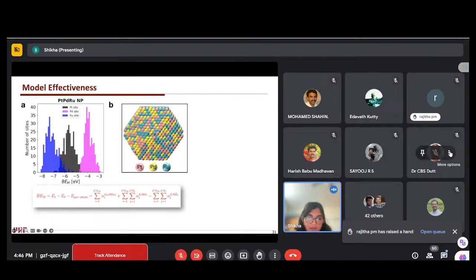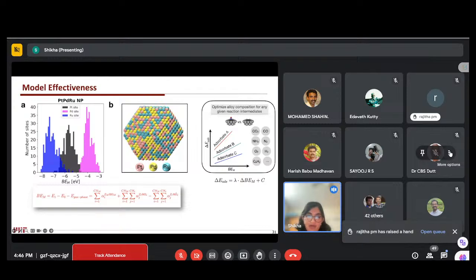Now we have a spectrum of the binding energy for a particular site. For a given chemical reaction, which range do I need to pick? We have a linear scaling relationship from which we can linearly scale the adsorption energy of a given reactant with the binding energy. From this linear relationship, we can see which region we should target to have the binding energy for a given adsorbate. According to that, I can tune the amount of platinum, palladium, and ruthenium atoms so that the statistics lie in a certain region.